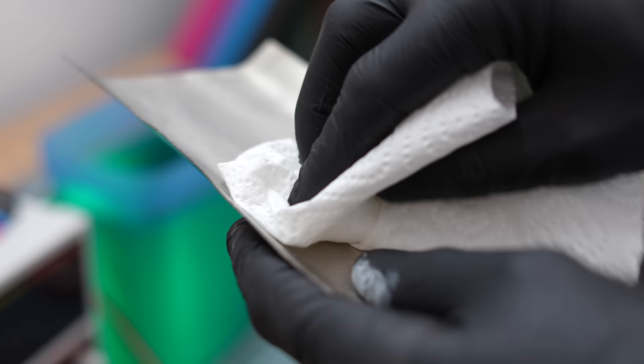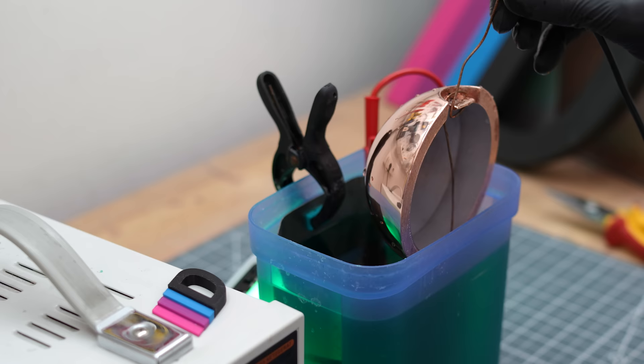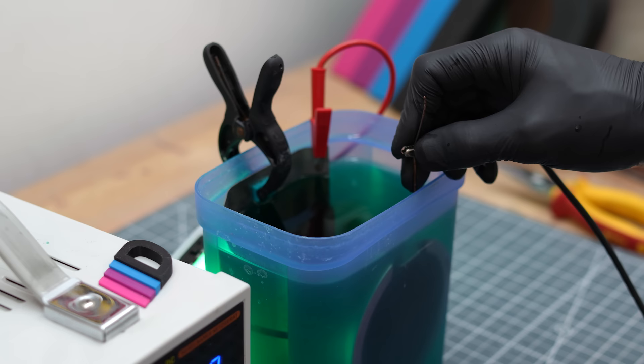Now activate a nickel anode with 10% hydrochloric acid, put it in the nickel bath and connect it. My nickel electrolyte works well at room temperature and I simply use around 2 volts. The whole process takes only a few minutes. Unfortunately, I'm already running out of space with these containers.